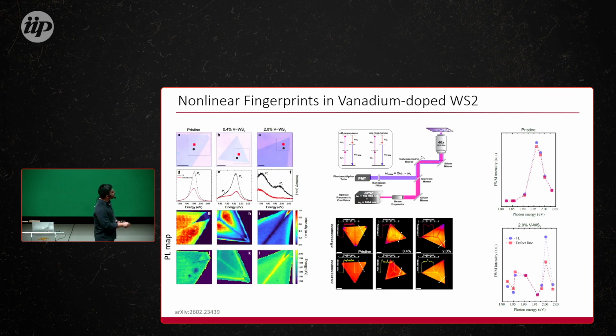And then when you go to the highest dopant sample, this is also shown, for this one I just didn't present, we can actually see it starts to get a little bit more sharp here, and there is a new state that appears here. So this is basically demonstrating that we are getting information using, in this case, the third order susceptibility. But this is a confirmation that the electronic structure is changing as well, and somehow seems to be in a specific geometry, right? So the next step was, how can I know the chemical cartography?